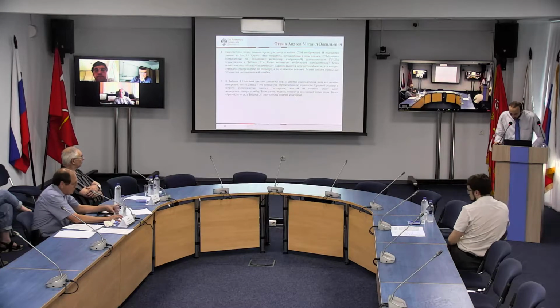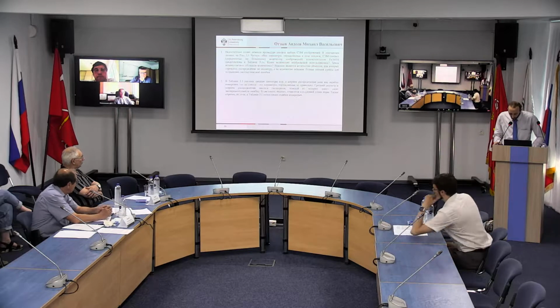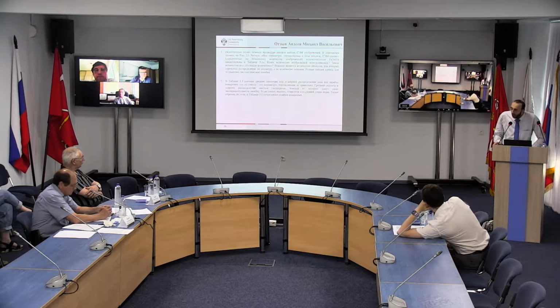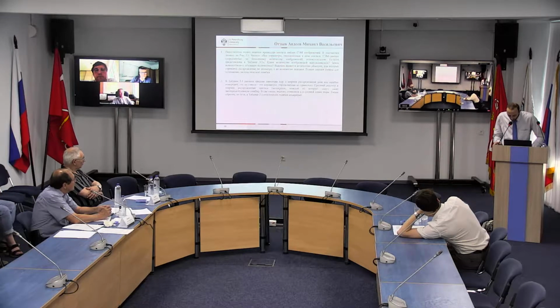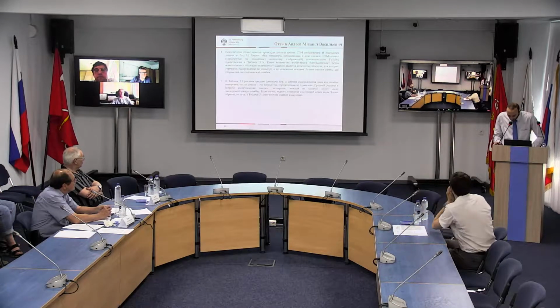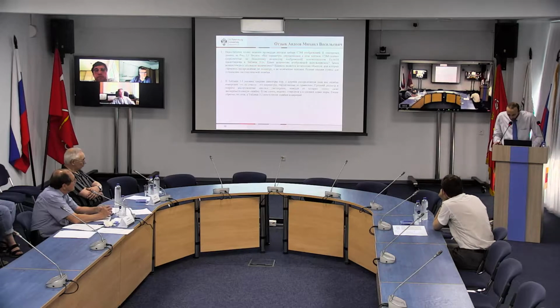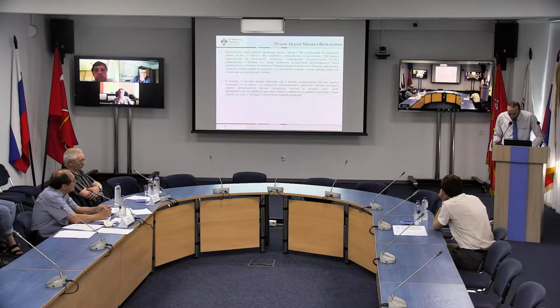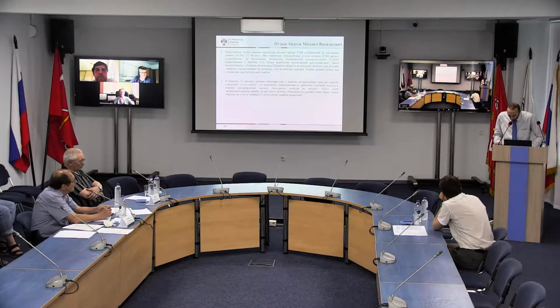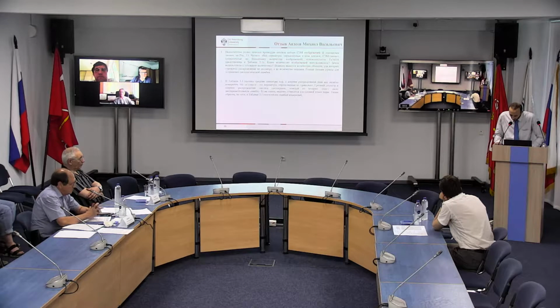Thank you for your valuable comments. I'll begin with the first comment regarding processing of same image. I agree with you that it should be noted particularly. For each sample, we processed about 15 images. In order to obtain higher statistics, we used images from different areas of samples. Additionally, different magnification was used. Large magnification gave lower statistics due to lower number of nanowires illuminated, but higher precision due to better resolution. For lower magnification, it's vice versa.